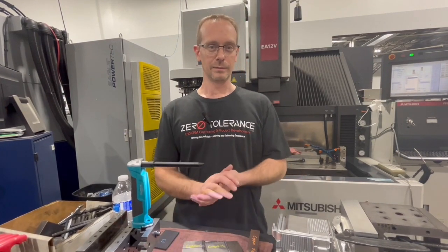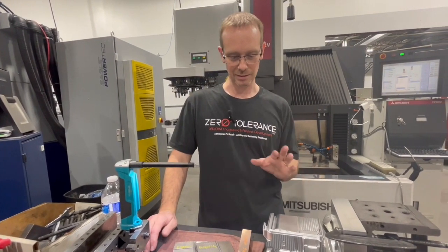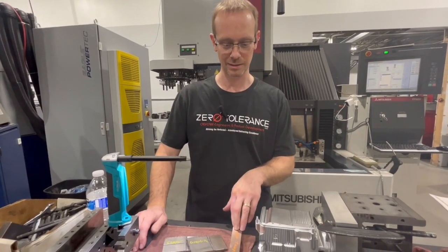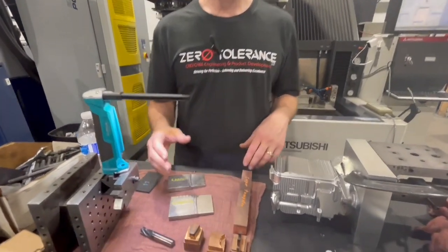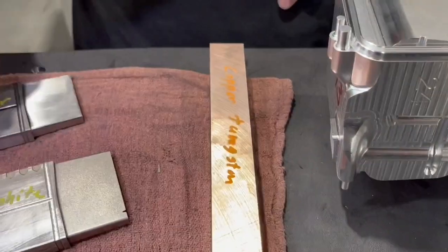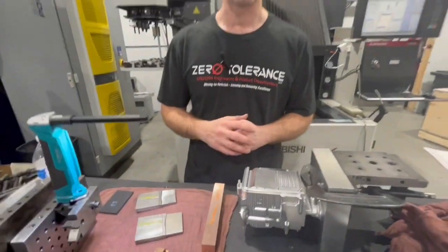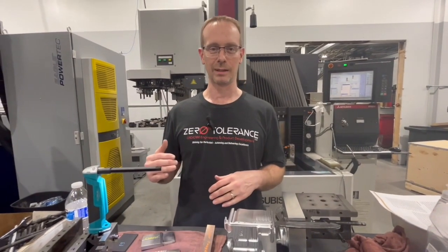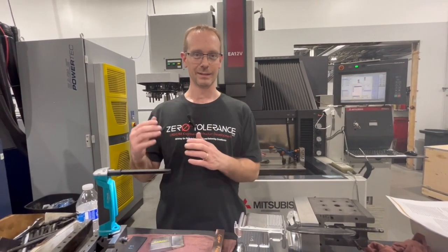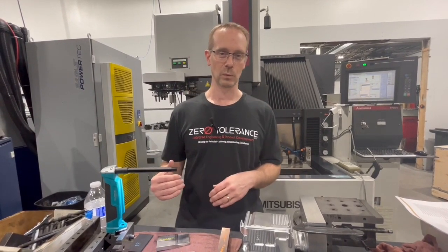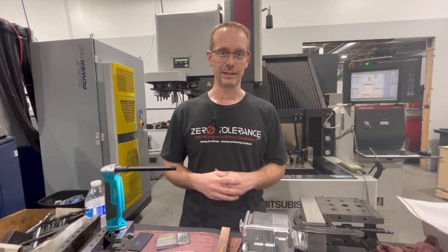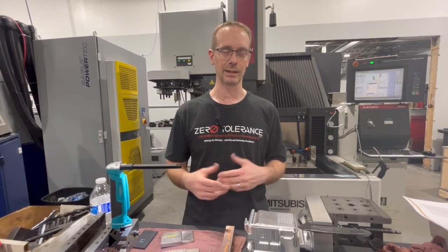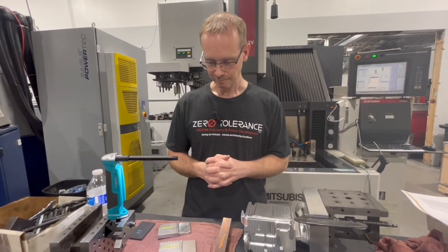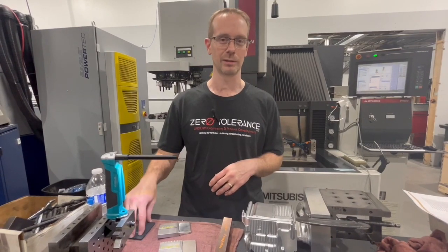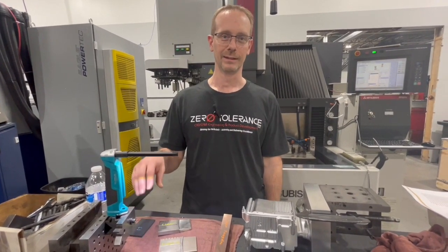So let's explore some of the other things about the copper tungsten that we didn't discuss earlier. As you saw in our last episode, we had the copper settings for the copper tungsten, and we didn't get a good result. We went from an hour and 10 minute burn with the wrong settings to 44 minutes of burning, which still is almost double the POCO 3 burn time, which was 22 minutes. So the advantage is still with the graphite for speed and cost.